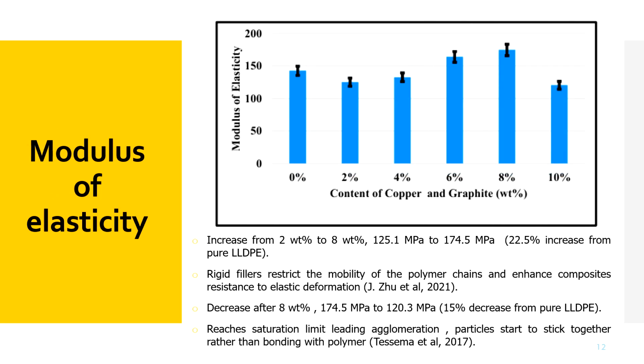In terms of modulus, we can see there are slight differences, whereby at 2 and 4% the modulus decreases. However, for 6 and 8% the modulus will increase, and for 10% we can see that the modulus also decreases if we compare back to pure LLDPE.